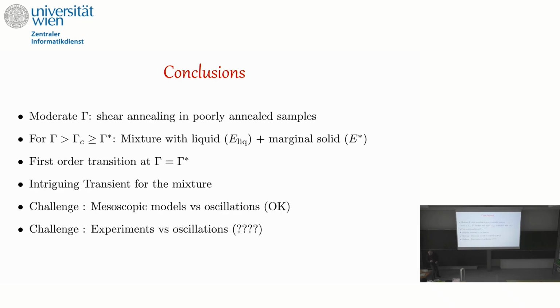One of the challenges that we had at the beginning was to transform the mesoscopic model in order to include this oscillation, and I think we understood what should be done, and we found results which are sound. Now I think one of the big problems, Roberto, it would be nice to see in an experiment if it's true that you have this shear annealing when you oscillate slowly and not fast. Thank you very much.